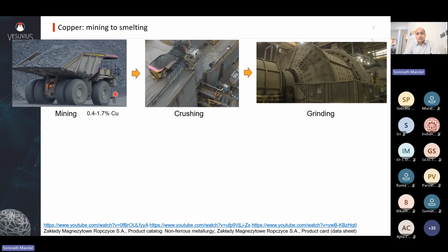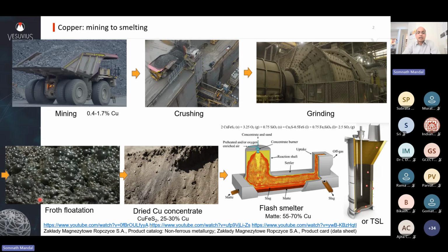So let's get started. First, after blasting and taking the ores out, they are crushed in big crushers. A lot of them are gyratory crushers. And then after that, it is ball milled into less than 100 micron particle size. From there, this fine wet ball milled slurry is mixed with some chemicals so that the main copper ore, which is CuFeS2, floats up, and this process is called froth flotation.